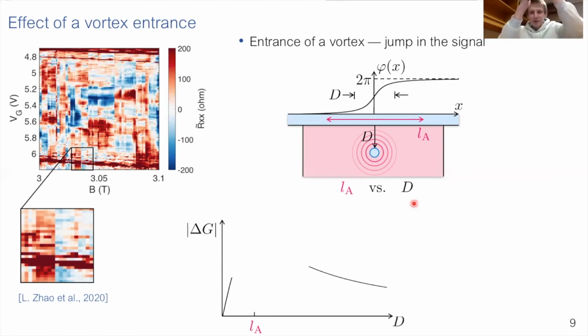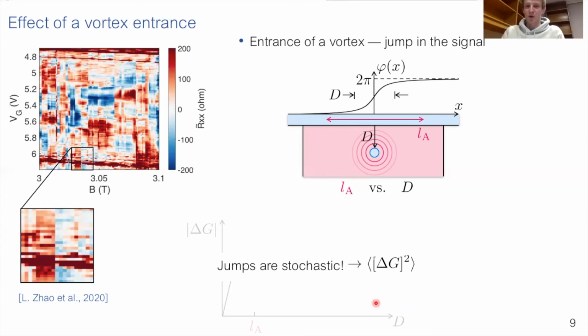Also, quite reasonably, if we move the vortex very far away from the boundary, it should also have no effect on the signal. And then the two asymptotics somehow interpolate in the middle, and there is some sort of a bell-shaped curve. What's a bit tricky is that the jumps themselves experience mesoscopic fluctuations, so they're also sensitive to the particular mesoscopic landscape. For example, you see that if we go along this vertical cut, the magnitude of the jump also fluctuates along this cut. So a question for which our theory can give predictions is what is the typical magnitude of the conductance jump.